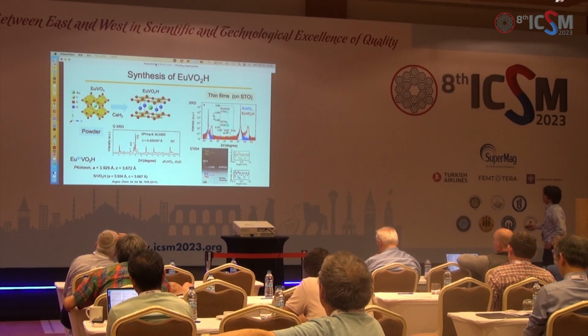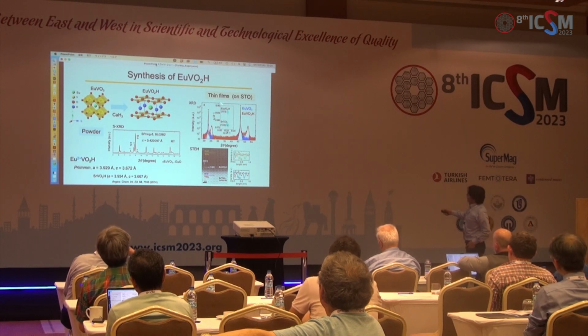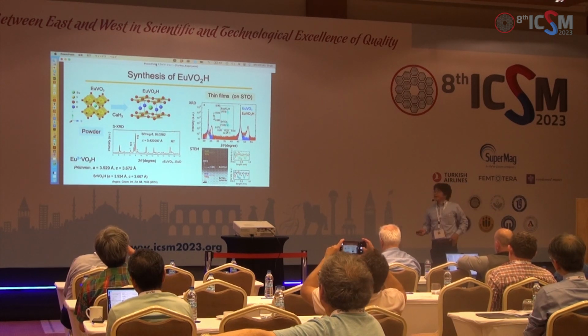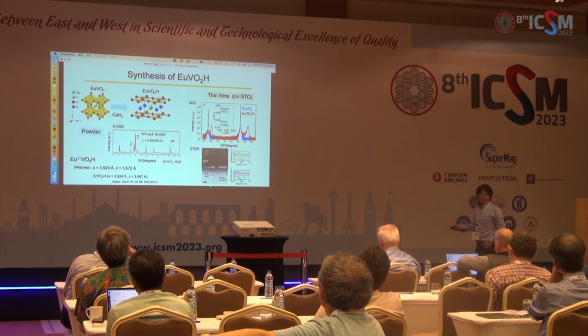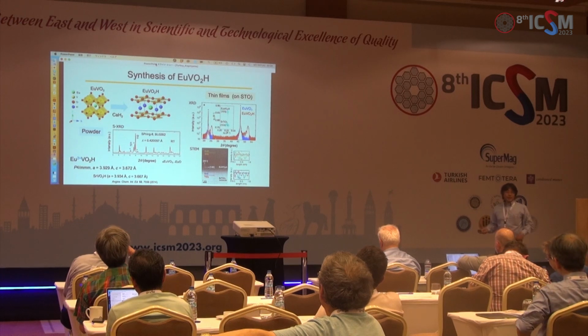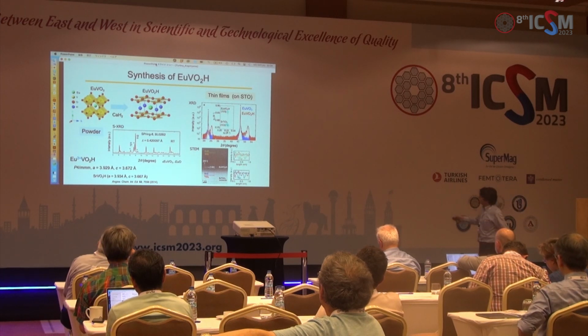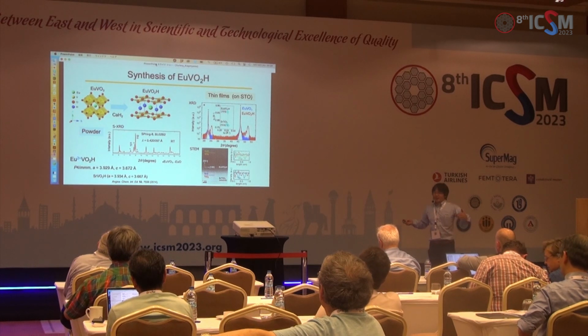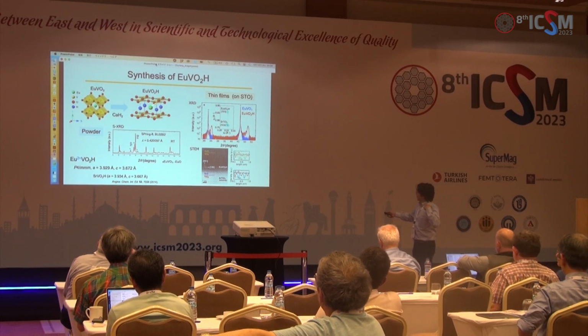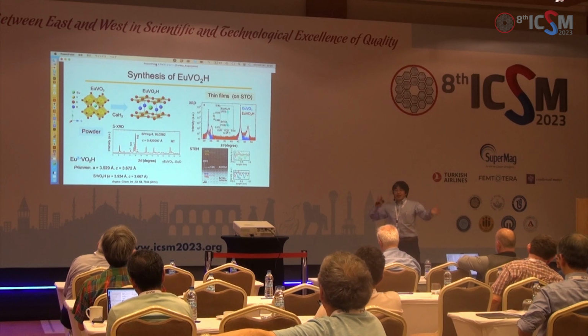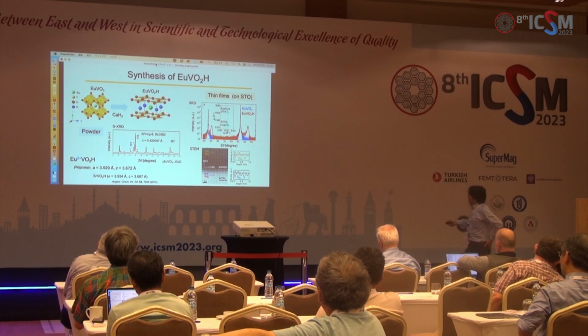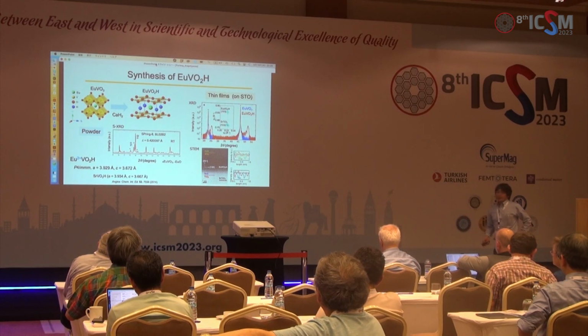Then we also prepare the epitaxial thin films, in this case using STO. Okay. Then the XRD and STEM images show the successful formation of this structure. But maybe epitaxial strain stabilizes this material. In this case, we didn't see any impurity phases. Okay. Anyway, we got this material, the same thing as well.